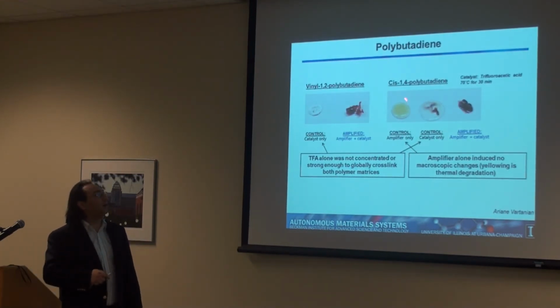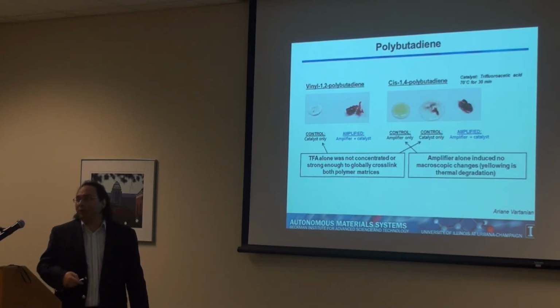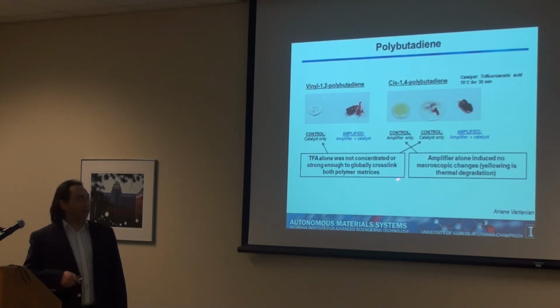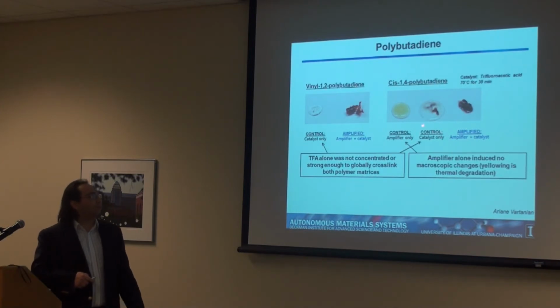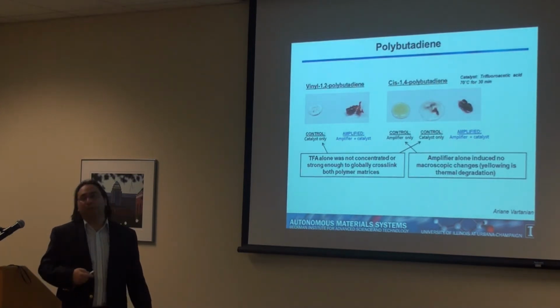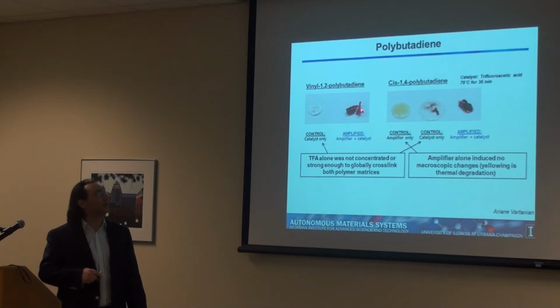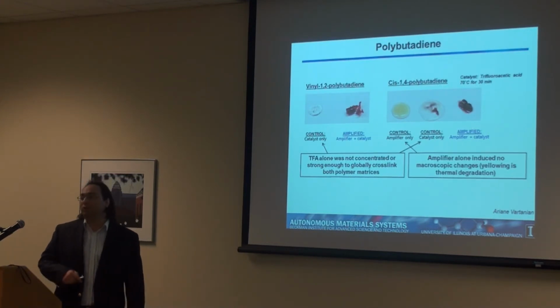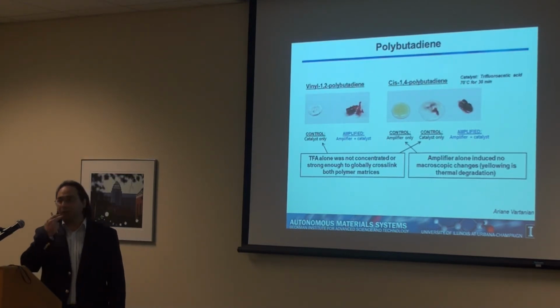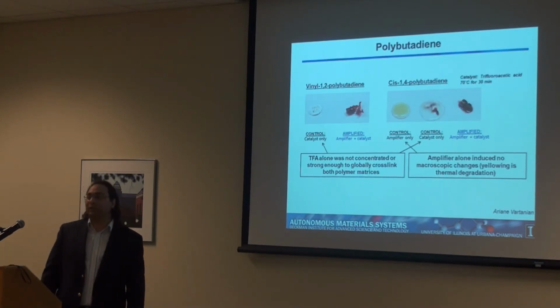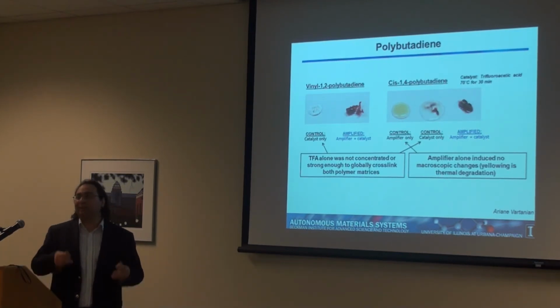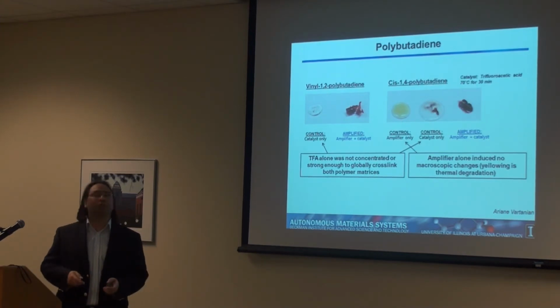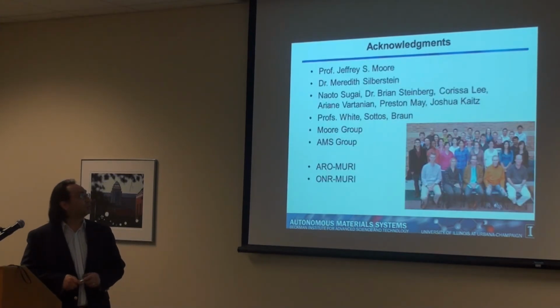But if you take a very low molecular weight polybutadiene, it's a liquid or it's a very viscous gel. And when we give it enough acid, it becomes solid, even a brittle solid. So it seems that this is the system we are going to work mostly on. The acid catalyzed reaction makes a significant mechanical change to this material.